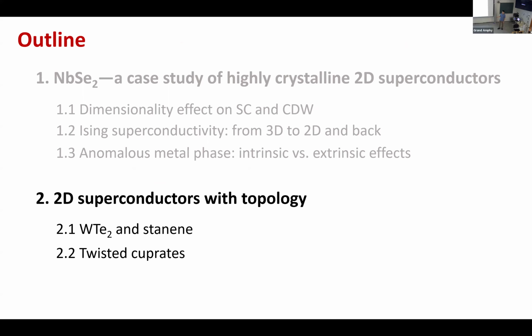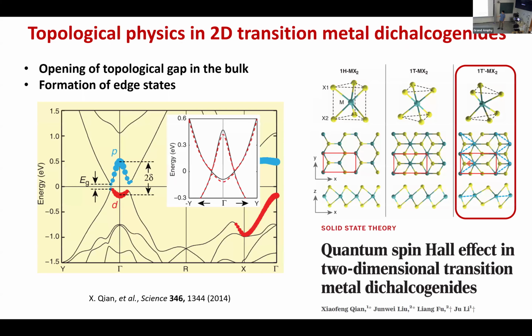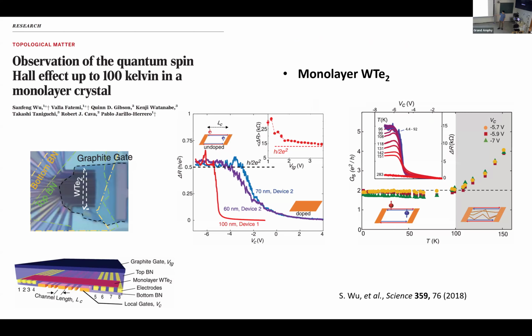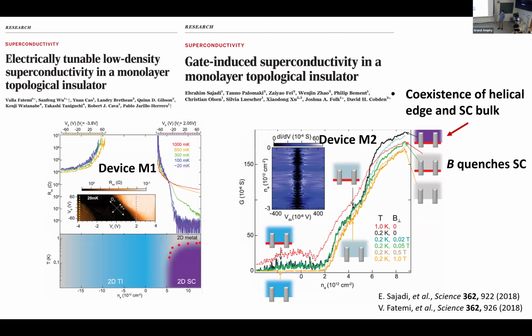And then, yes, maybe a few minutes, I will just skip this, because these are just topological insulators in the 2D limit, the monolayer, and they claim they could observe the quantum spin Hall effect. When they inject a lot of charged electrons, this system becomes superconducting. So, as the title says, this is superconductivity in a monolayer topological insulator. So this is a topological insulator that can superconduct, but that doesn't mean it's a topological superconductor.